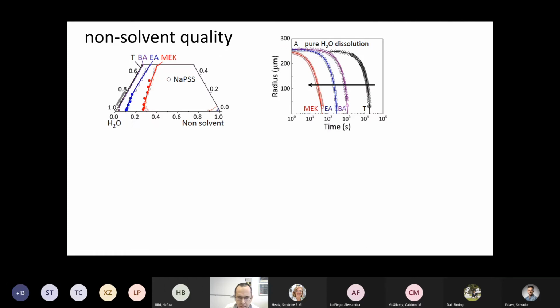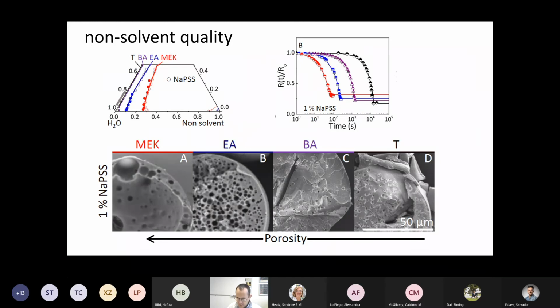So, does this work? Is it really that simple? We take here four solvents, a solvent with an extremely low selectivity, one which is considerably faster, and you realize it's slightly counterintuitive that the one that is the slowest is actually the one that gives you the smallest and the more compact particles. After you say it, it kind of makes sense.